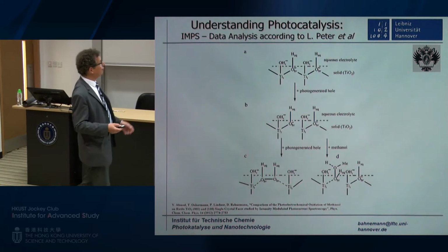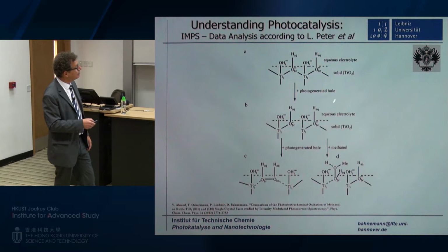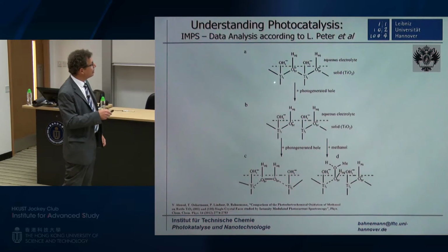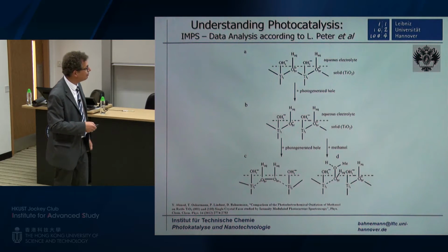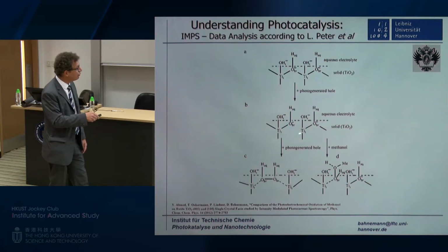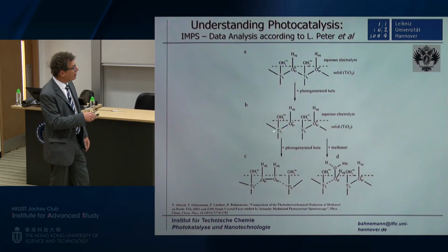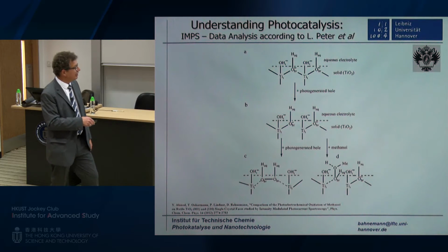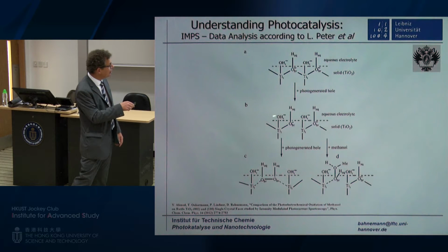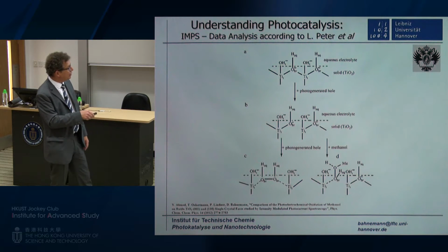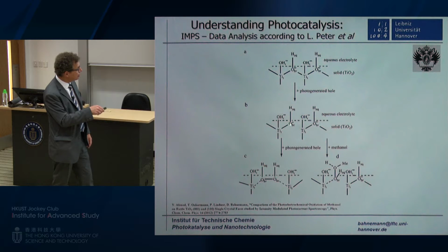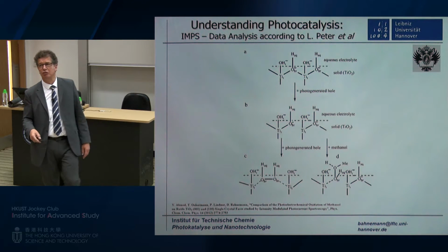Case 2 can have different ways of reacting. One way would be that you are oxidizing mainly the terminal hydroxyl groups, but we don't think this is happening. I tell you in a minute why. We think what is happening is that you have bond breaking in your TiO2. The oxygen that we are talking about is not an oxygen from the water, but is an oxygen from the TiO2 matrix. So your case 2 means that you oxidize this bridging oxygen and probably this bridging oxygen, and then you get an oxygen-oxygen bond through the oxygens from the TiO2 matrix.